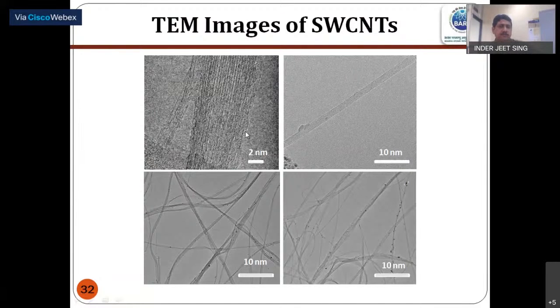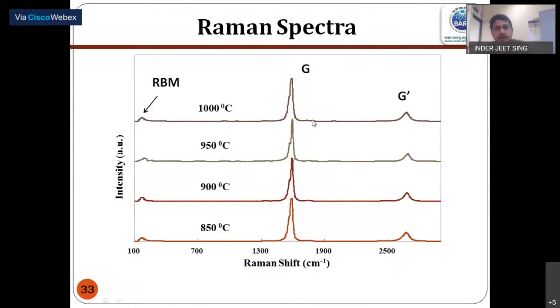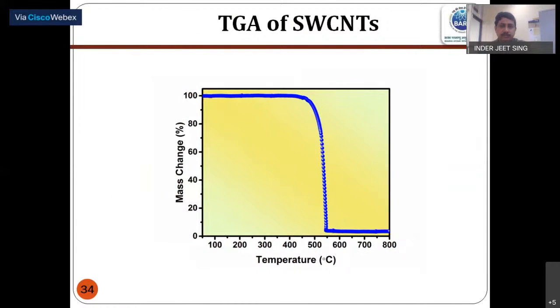So this is typically the TEM of that single wall carbon nanotube. Generally all single wall carbon nanotubes are present in a bundle. So you can see a lot of single wall carbon nanotubes here. But then in the Raman, we don't see the D peak, which was present in multi-wall, and here the RBM peak comes. So by seeing the Raman, you can understand whether whatever you have produced is single wall or multi-wall. And from RBM you can also find out the diameter of the carbon nanotube. Now, if you see the TG, this is very sharp, and only a single peak is supposed to come in a pure single wall carbon nanotube.